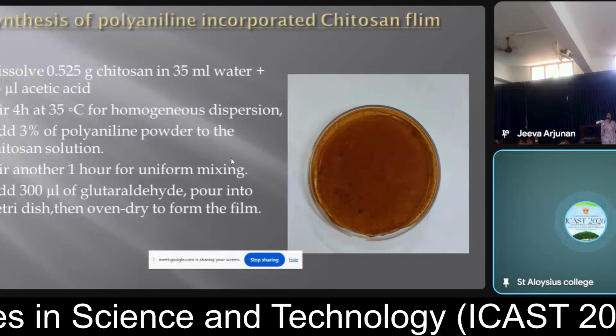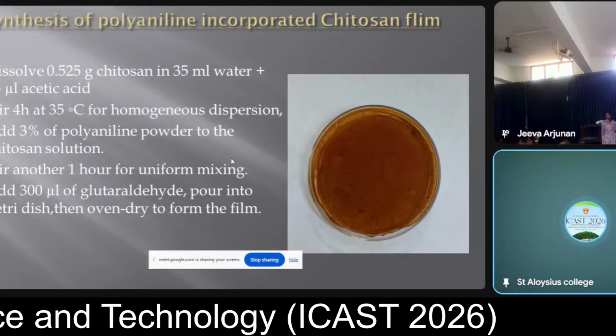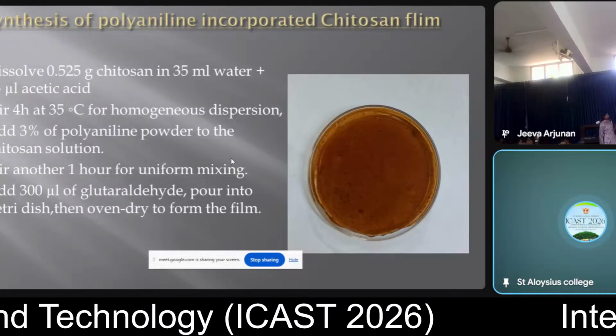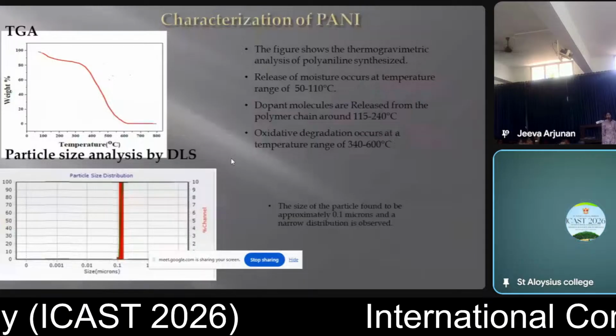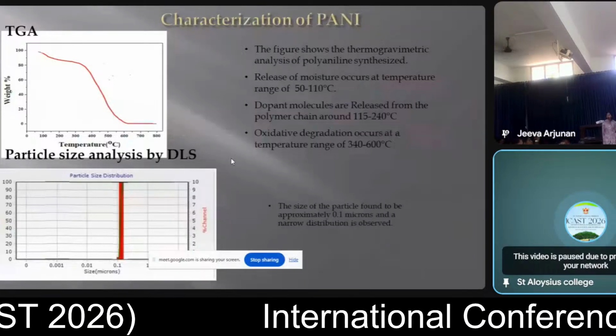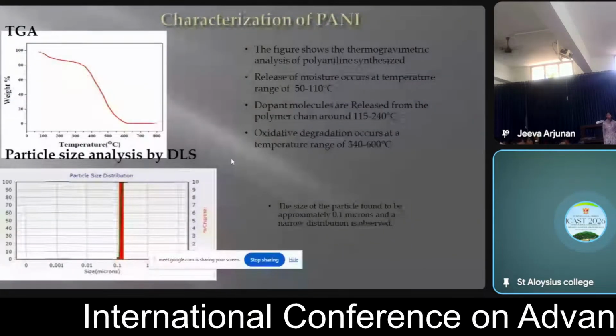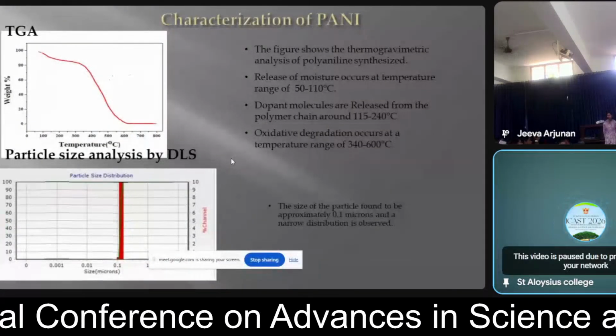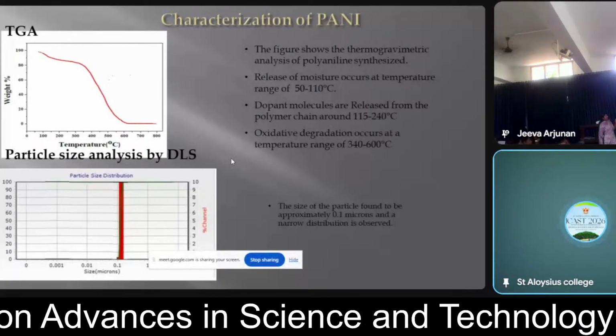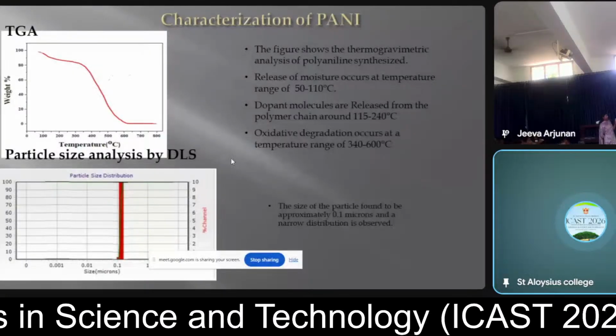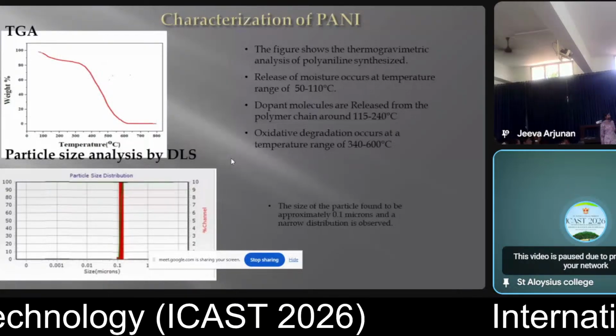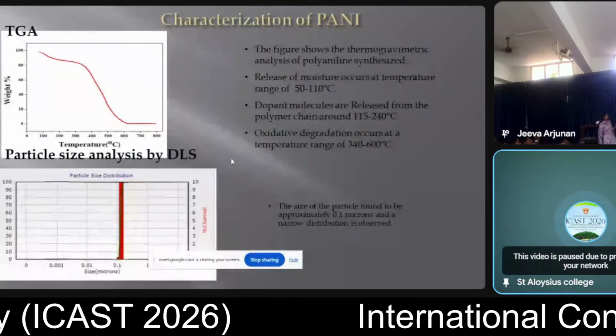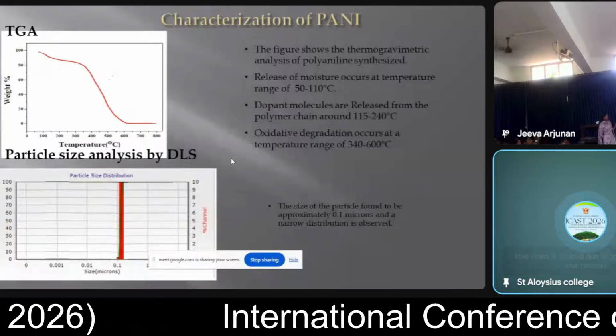We characterized polyaniline. The first characterization method we used is thermogravimetric analysis, and the next is dynamic light scattering. From thermogravimetric analysis, we found there are three decompositions. The first is the release of moisture, the second is the release of dopant molecules, and the third is the oxidation of the polymer chain. The release of moisture happens at 50 to 110 degrees Celsius, the dopant release happens at 115 to 240 degrees Celsius, and then comes oxidative degradation. That's why we call it stable. The particle size is approximately 0.1 microns.